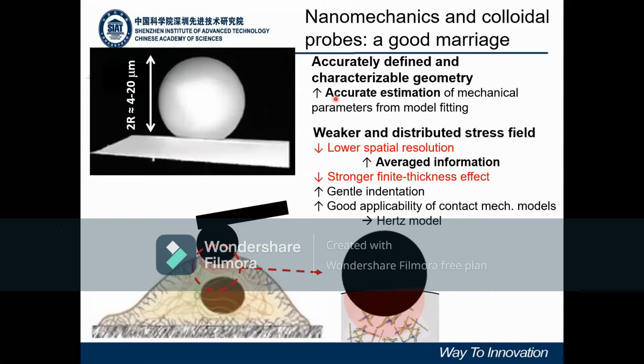In this case, we can have a good estimation of the geometry of the probe because it's a sphere and so very easy to measure. Plus the pressure applied to the sample is smaller, and the indentation is gentle. And then a very easy linear model, like Hertz, can be applied. On top of this model, corrections can be overlapped for measuring the viscosity or the finite thickness, when the sample thickness is small compared with the indentation.